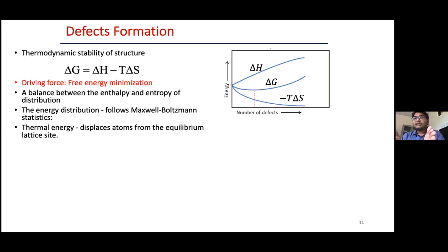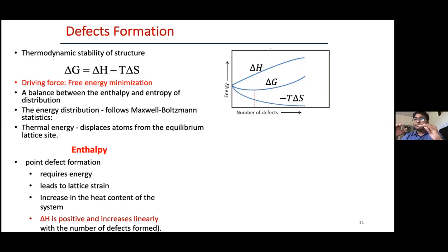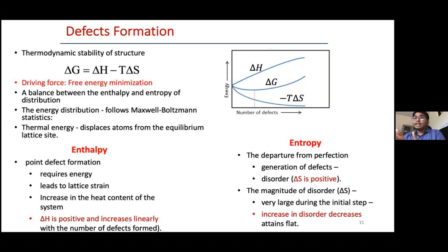So there is a trade-off between the enthalpy and the entropy, between the two things. The enthalpy, basically, we know, is the amount of energy required for this defect to form, and it is supposedly a positive quantity, and it goes on increasing as you go on creating more and more defects. However, the entropy, on the other hand, is also a positive quantity, but now they are going to balance each other, right? So as the temperature increases, the disorder in the system goes on increasing, and that somewhat stabilizes this thing.